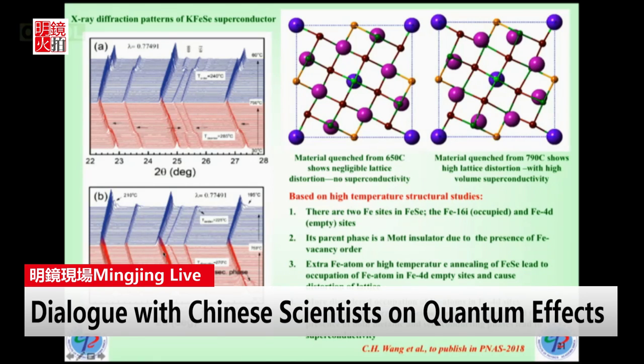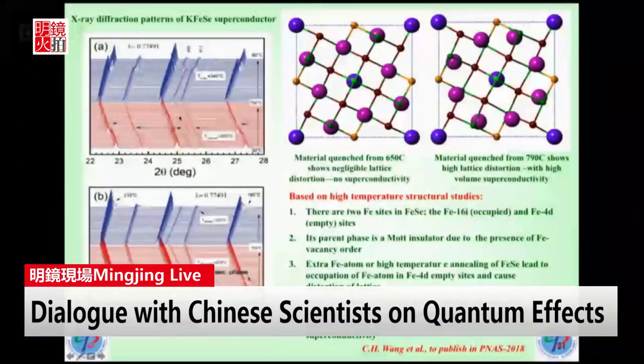And here I show you the X-ray picture, showing where there is some diffraction peak. I just wanted to point out the key feature. For the non-superconducting one, look at it here. We are probing this from room temperature, going up to a very high temperature. Suddenly, this peak shrinks, right? Changing from these two positions to that. Okay, so this is the insulator material. However, when it becomes superconducting, you see that the X-ray position doesn't move at all. Okay, this is the experimental data.